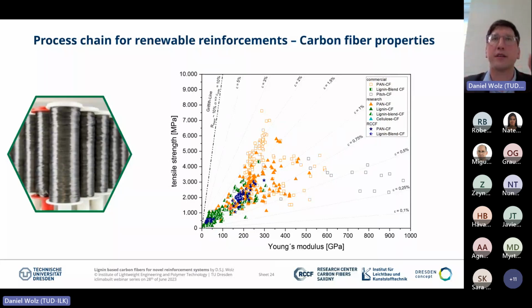If you look at this slide, you see for one point the maximum elasticity, also the maximum extension, the break extension for carbon fibers, ranging at about 10%, determined by Griffith's law. On the orange side, this is carbon fiber, in the commercial and research way. If you look at the lignins, we see that we have much fewer possibilities developed as for application.